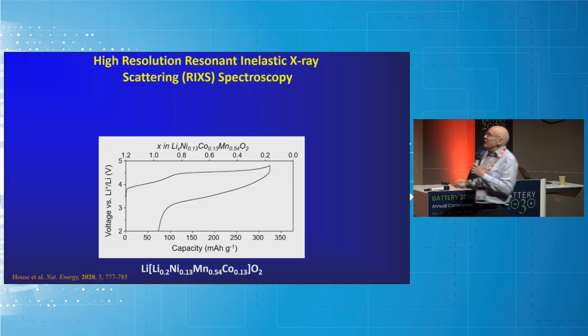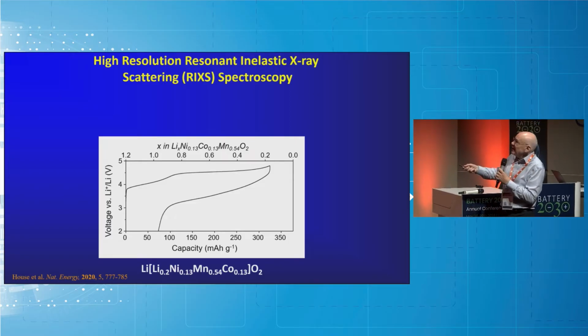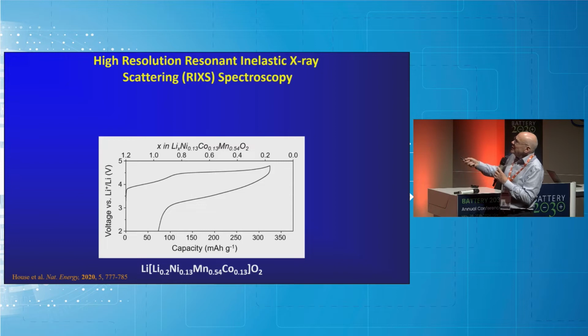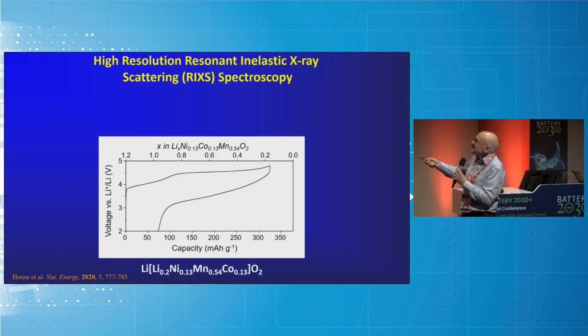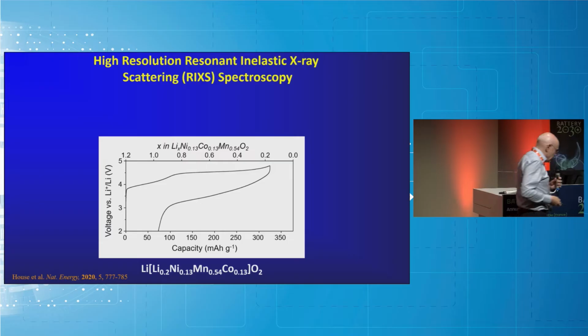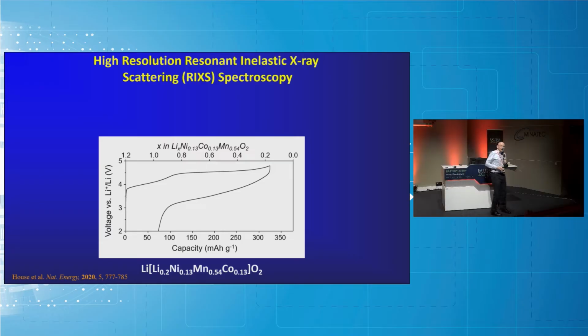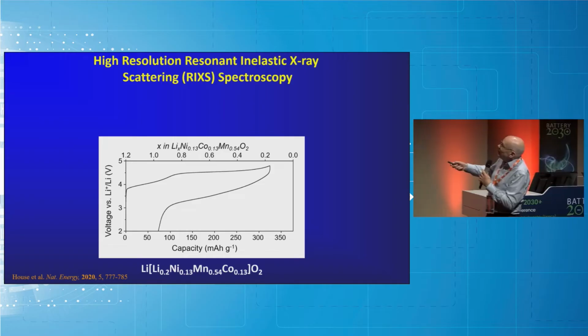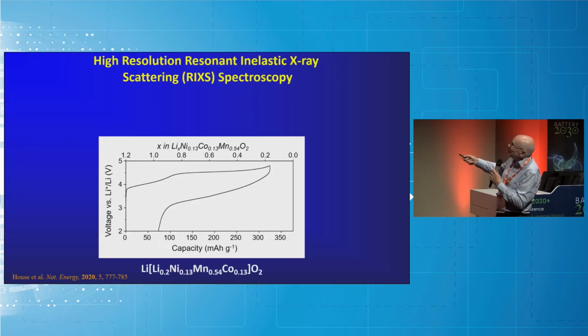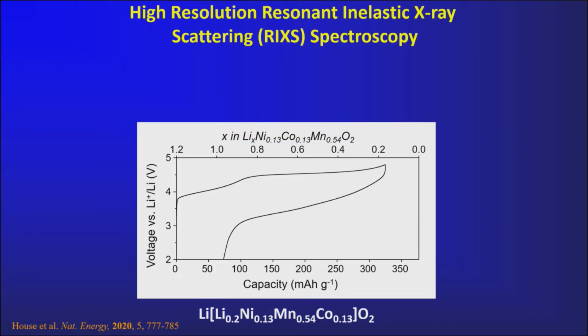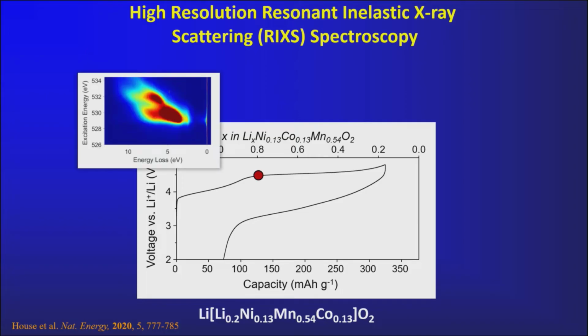So what I'm going to show you now is that load curve again. Same compound. I'll spend a lot of the time using this classic lithium-rich NMC as the exemplar, but the same thing happens in other lithium-rich compounds. We're going to go along this charge-discharge curve, and we're going to take some snapshots of the RIXS spectra that we see as we do so. So if we start at this point here, this is the beginning of the plateau. Remember, this is the region where we're stripping electrons from oxide ions.